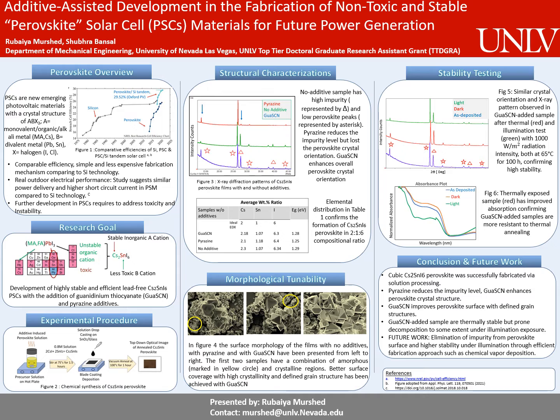As solar cell materials are exposed to light and temperature, it is important to test the stability of perovskite cells under these atmospheric conditions. Figure 5 presents the X-ray diffraction pattern of the perovskite crystal structure exposed to light and dark thermal treatment at 65 degrees Celsius for over 100 hours. We can see a similar pattern after the stability treatment compared to our reference as-deposited sample. However, we have observed a slight change in the intensity of the peaks.